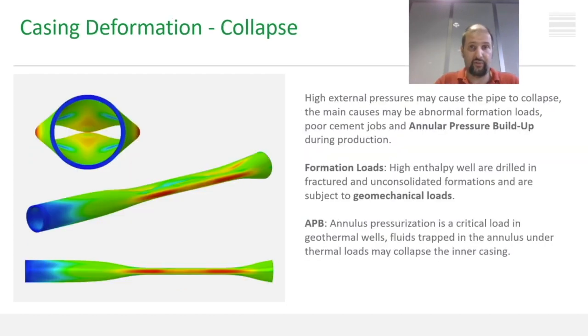Other than compression, another typical well load for geothermal application is collapse, which is typically the cause of casing ID restrictions. In geothermal wells, there are several sources of collapse loads: the reduced backup pressure from the produced fluid, for example steam, annular pressure buildup, partial evacuation due to highly fractured formations or incomplete cementing jobs, and so on.